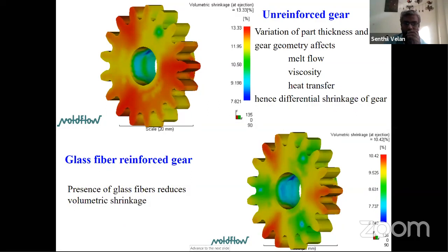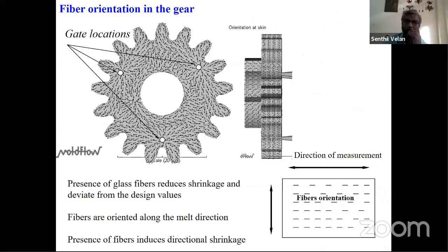Not only is it dropping the shrinkage, which means you have to adjust the part cavity accordingly to compensate, but the issue does not end with that. If you look at the orientations, the fibers are discontinuous, so they are going to orient along the melt flow direction. Again, this is simulation; I will show the actual picture towards the end. The glass fiber reduces shrinkage and the fibers are oriented along the melt direction. This is your point of gate, and the melt is flowing outward, so it is aligned with the ends of the profile.